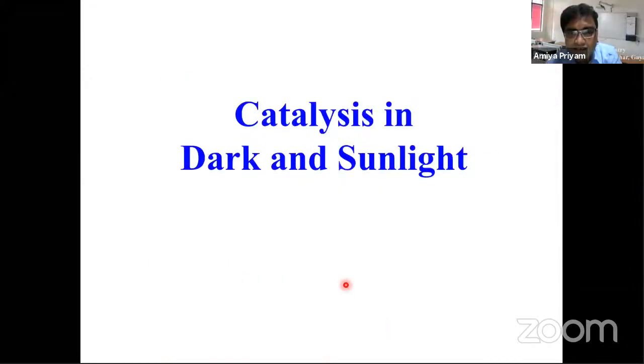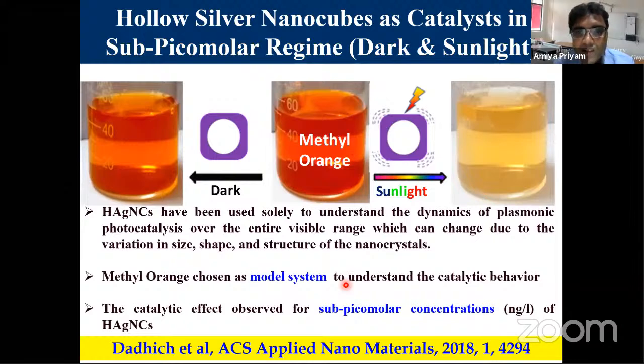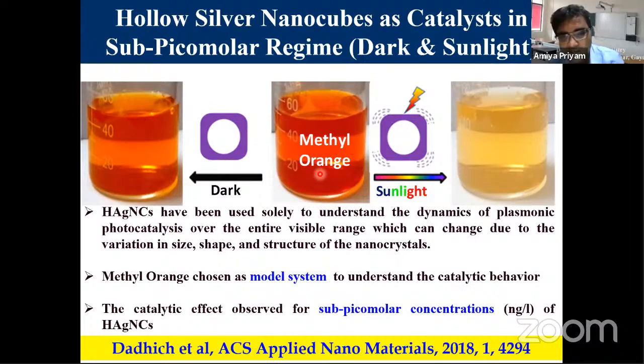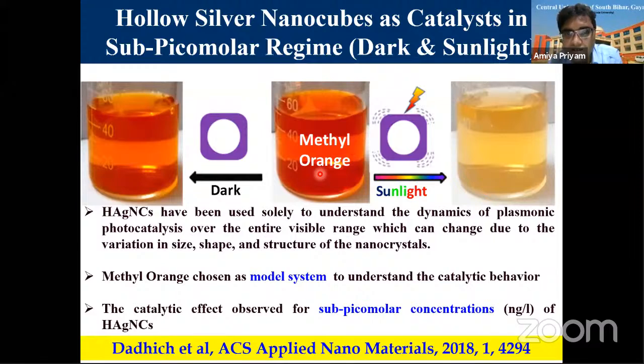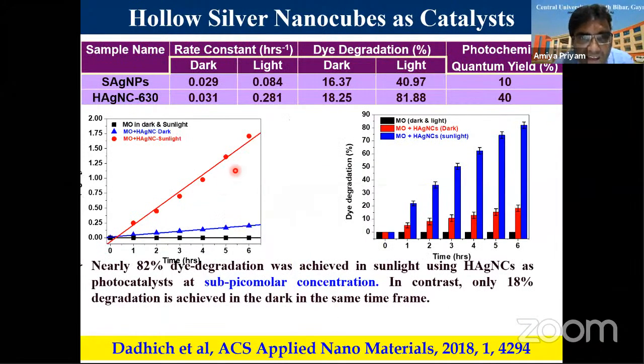And the second application is catalysis that we did using these hollow silver nanocubes. We can show that it can act as a catalyst in presence of sunlight, and also weakly it is a weaker catalyst in the dark, but it is a catalyst. So it is a different method. The model system here was methyl orange, and the degradation was catalyzed by these silver nanoparticles. We could also establish that as we move into the near IR range towards the red side, the nanoparticle with 630 nanometer SPR peak acts as a better catalyst as compared to the nanoparticle which absorbs at 400 nanometers. So clearly moving into the red makes sense even in catalysis.